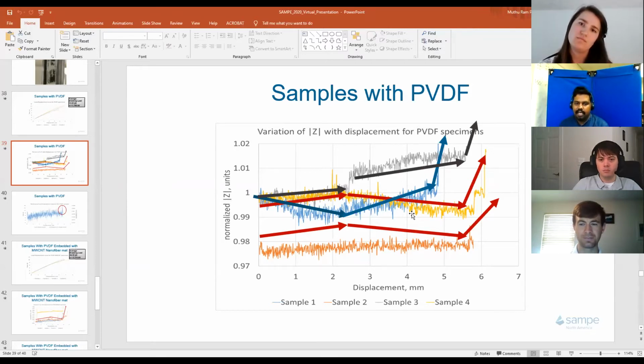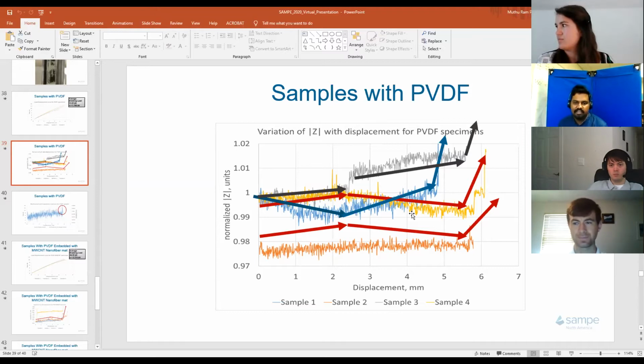We had different thicknesses in the samples, and with 4 samples we cannot conclude what was happening. Even for all the 3 experiments, we had only 4 samples of data. Since this is a unidirectional material and all were at 0 degrees, we had to use tabs, and we had to bond the tabs onto the specimens, and the specimens were also not clean. So we feel surface contamination is the main reason, because the sensors were not cleaned properly and the samples were not cleaned properly with the bonds. So that might be one of the reasons, but we are not sure of it exactly.